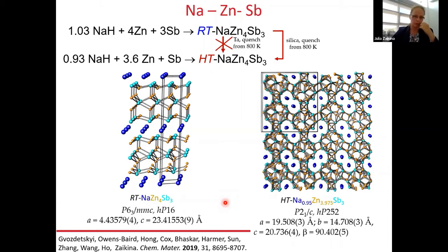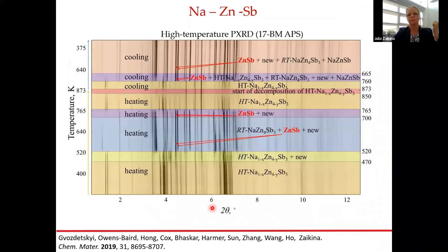So with this initial success, we were curious whether other compositions are available. And so for that, we again brought this high temperature phase to the Argonne National Lab. And upon heating, what we observe is that at a certain temperature, we start to see new diffraction peaks, which cannot be assigned to something else. So in this particular system, because the high temperature diffraction experiment was performed in a silica tube, we again have a method to slightly shift our composition toward sodium deficiency, because sodium really likes to react with silica. So we start with this composition, which is close to 143, but then upon heating, it's not only temperature which is changing, but also the composition.